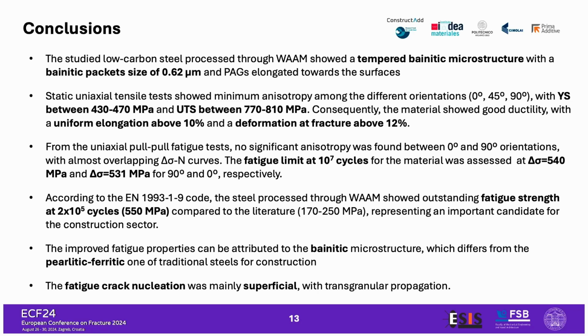But since the material is intended to be used in the construction sector, we also assessed the fatigue strength at 2 by 10^6 cycles being delta sigma 550 megapascal, which is an outstanding result that we attributed to the very fine novel microstructure obtained by the wire arc additive manufacturing process. And finally, we observed fatigue crack nucleation was superficial with the transgranular propagation.